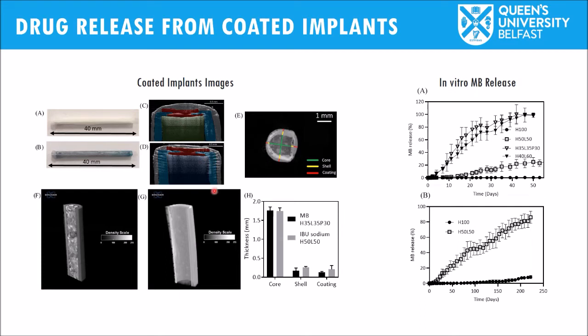Micro-CT was used to characterize them, measuring the thickness of the coating and the dimensions of the implant, and the methylene blue release was evaluated in these implants. Interestingly, the films prepared using high molecular weight polycaprolactone didn't provide any release. They were quite water impermeable, but as soon as low molecular weight polycaprolactone was included in the formulation of the films, the release rates increased, and by changing the proportion of polyethylene glycol and low molecular weight polycaprolactone, you can have different types of release.